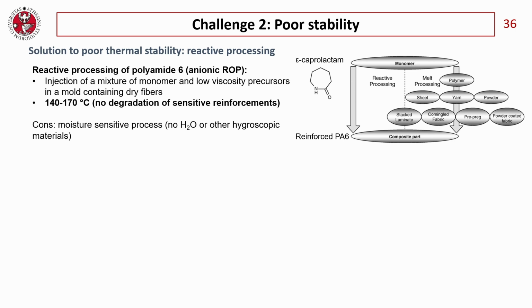Okay, another solution could be changing completely the processing of thermoplastics. If we substitute the traditional thermoplastic processing with a reactive processing, we end up working at a lower temperature, and this could be a solution not to overcome the famous 200 degrees Celsius. This can be done not with all the thermoplastics, but only, for example, with polyamide 6.